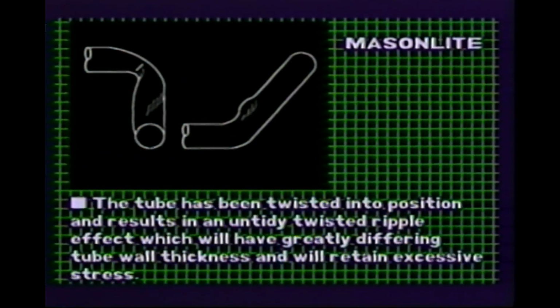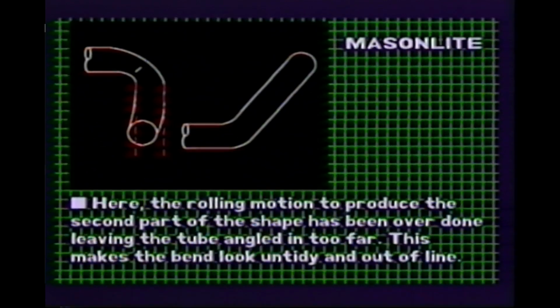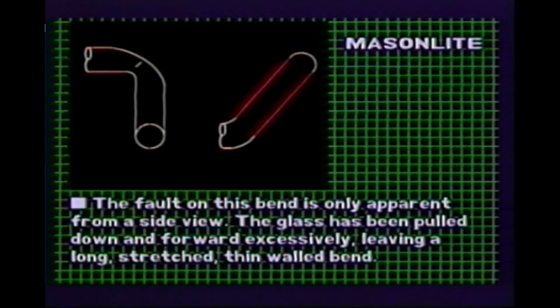In this example, the tube has been twisted into position, and the result is an untidy twisted ripple effect, which will have greatly differing tube wall thickness and will retain excessive stress. Here, the rolling motion to produce the second part of the shape has been overdone, leaving the tube angled in too far. This makes the bend look untidy and out of line. The fault on this bend is only apparent from a side view. The glass has been pulled down and forward excessively, leaving a long, stretched, thin-walled bend.